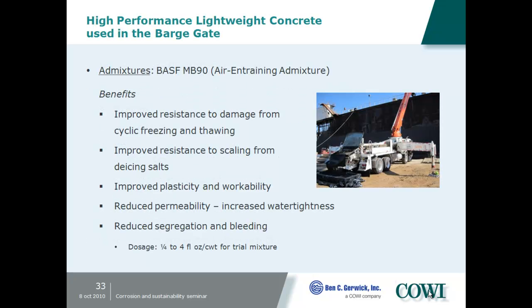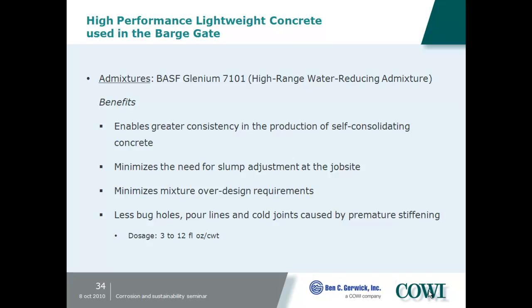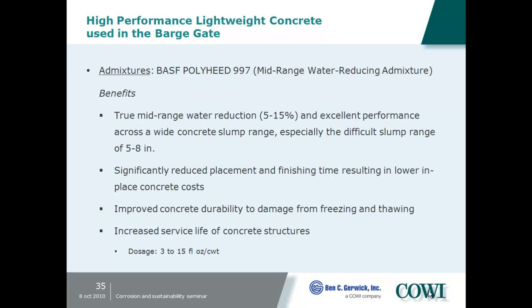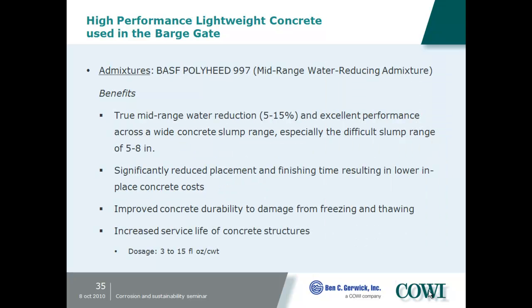And again, we did use air entrainment. It decreases the permeability, decreases the bleeding. Here's a high-range water reducer to try to get around all the rebar. Mid-range water reducer, try to extend its slump life, since often the high-range water reducers lose slump, and then this provides a backup at a good price. But also it has other advantages with regard to finishing with this admixture. It improves the concrete durability against freeze-thaw, this particular admixture.